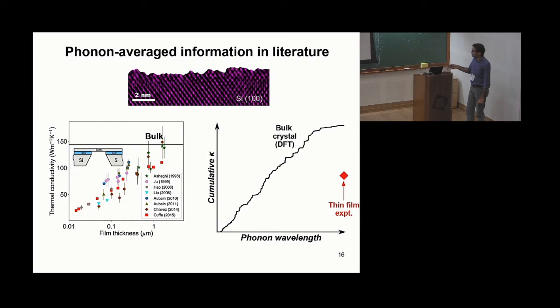These are a large volume of literature I have accumulated for thermal conductivity as a function of film thickness for silicon. You can see that when the film thickness is very large, more than 1 micron thick, the thermal conductivity is close to the bulk value.